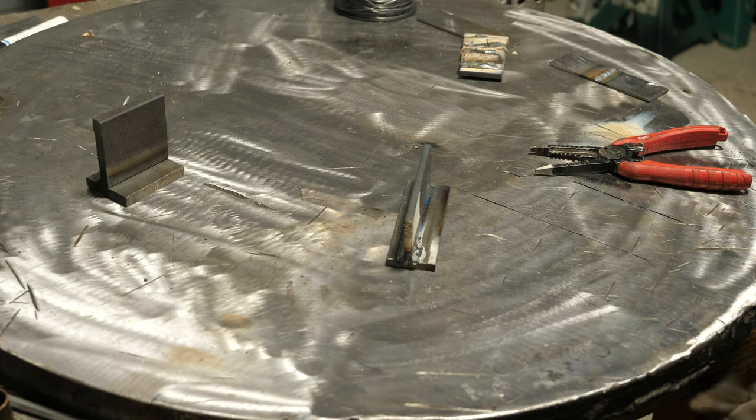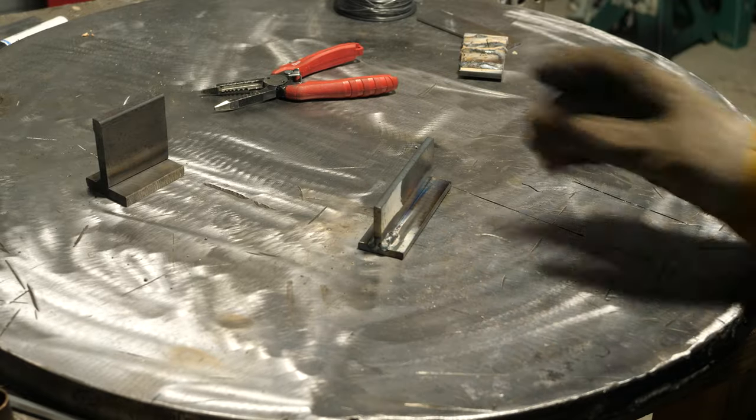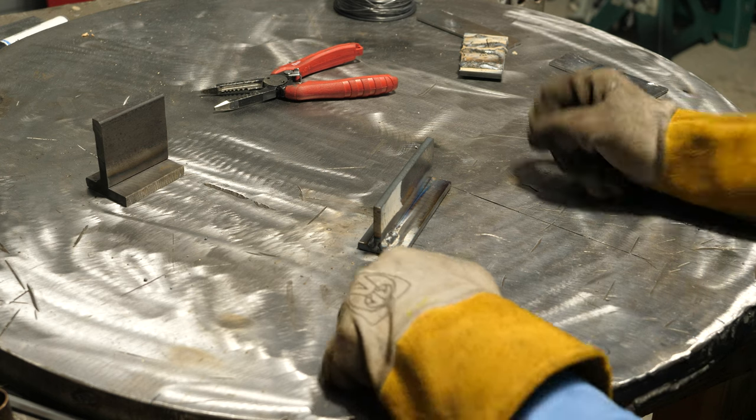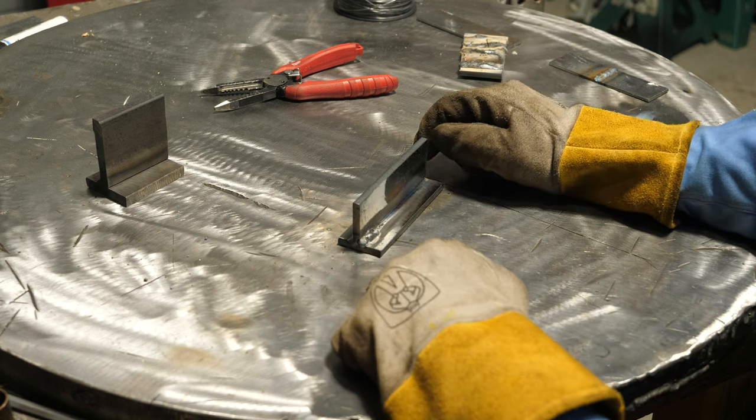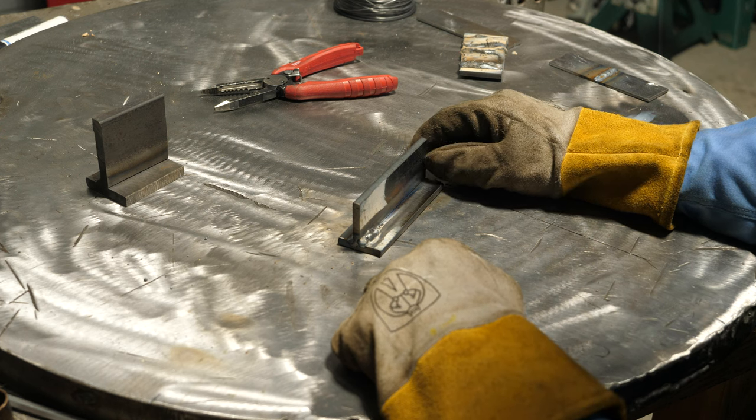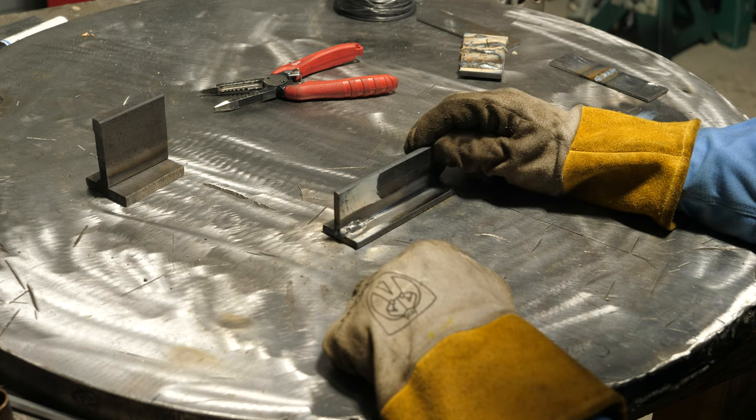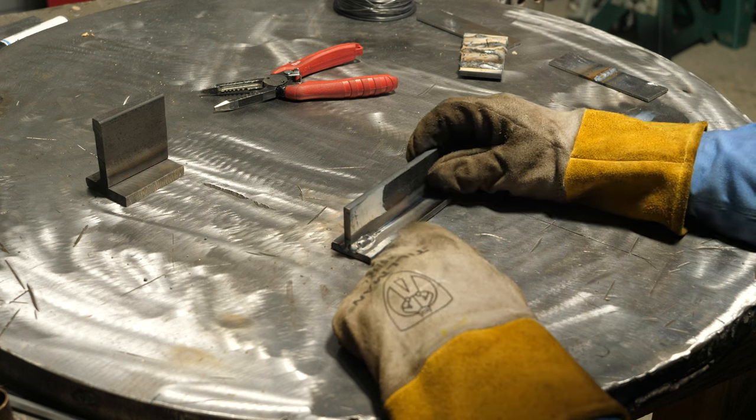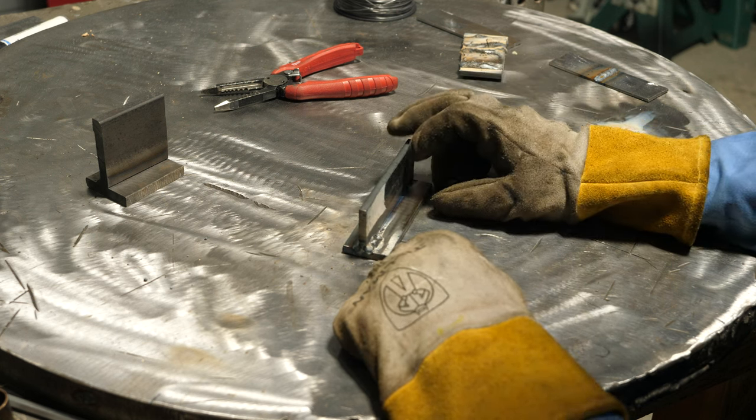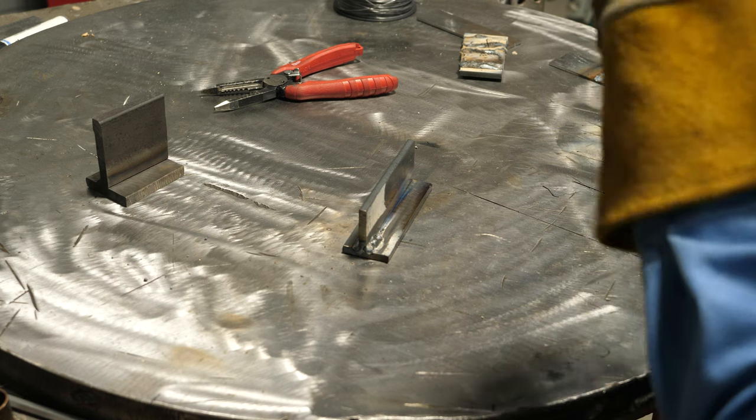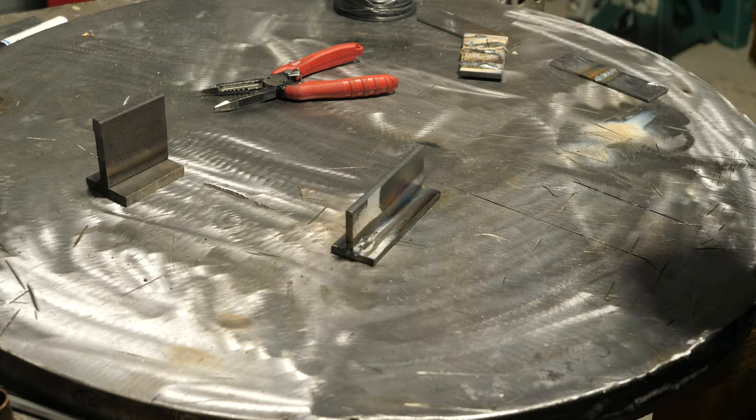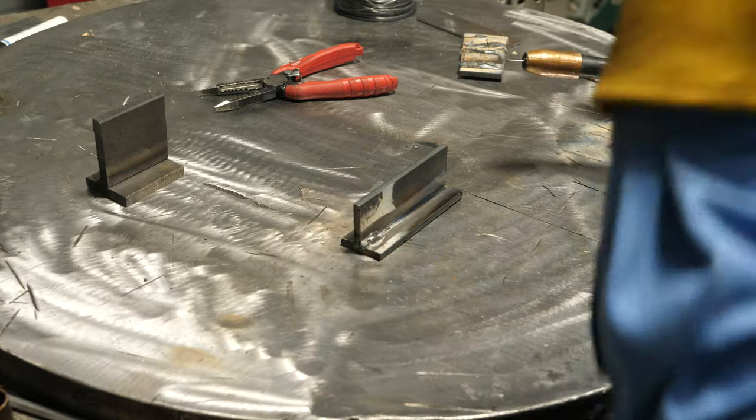All right, so generator kicked out because it didn't have enough power, story of my life here. So I reduced the settings. We're gonna run about 325 and 19.5, that's gonna put us in the ballpark somewhere around 170 amps, which is a little bit on the low side for this quarter inch plate. But it should work and we should definitely see a difference between this and the MIG weld on the other side. So let's weld it.